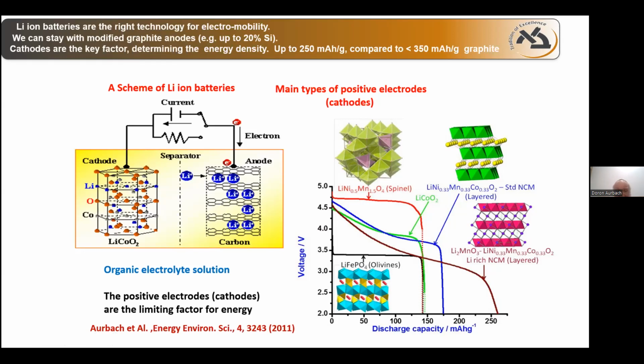I should say that within systems comprising lithium carbon compounds, lithium transition metal oxide, and the organic electrolyte solutions that we use, and we will discuss some of the organic electrolyte solutions, there is no thermodynamic stability, never. So lithium-ion batteries are always metastable. They lean on very complex passivation phenomena that we'll discuss later on. So we're talking about very delicate passivation phenomena that allow the operation of lithium-ion batteries. We could really give up the specific capacity of the negative, because what is limiting is the positive.